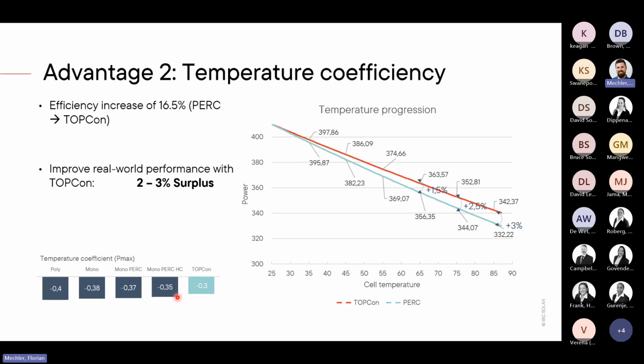But when you look at what the difference is in percentages, it's 16.5% as a differentiation. And that means we have an efficiency increase of 16.5%. What does this mean for a module? I said both the PERC module and the TOPCon module start with 410 watts. And then we see what happens when the cell temperature increases. The line goes down and the cell temperature goes up. Normally, I would say for South Africa, it's between 75 and 85 degrees.